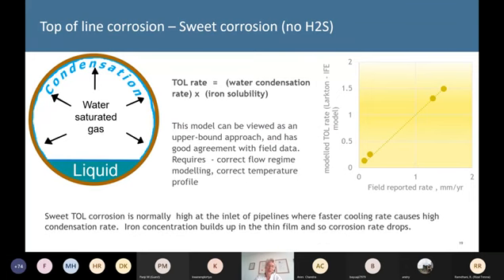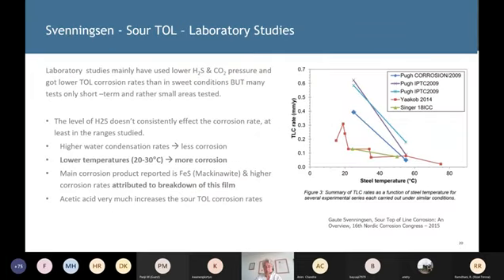Quickly moving on, the top of the line corrosion in sweet systems has been extensively studied, and it's shown that the top of the line corrosion rate is related to how fast we've got condensation taking place and what the solubility of iron is. So if we've got fast cooling rate, then we get a high condensation rate and a high top line corrosion rate. But as the iron concentration builds up, the iron solubility drops, and so the corrosion rate drops off. And we've got modelling related to this, and this is a pretty reliable model for sweet corrosion and has been used in many of the models globally.